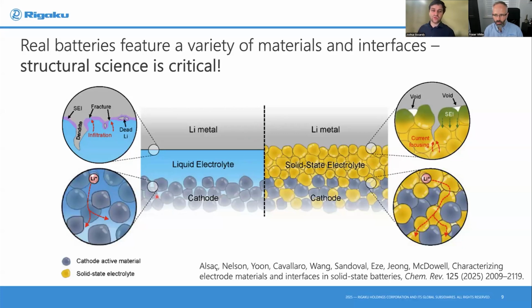As you charge it, you can also imagine that the cathode is going to lose some of the lithium, and that is going to cause it to shrink in size or grow in size, depending on the chemistry. There could be stresses, strains, cracks, additional side products, gas evolution. And so understanding all of these processes is really the key to understanding how batteries work and how to make a better battery.